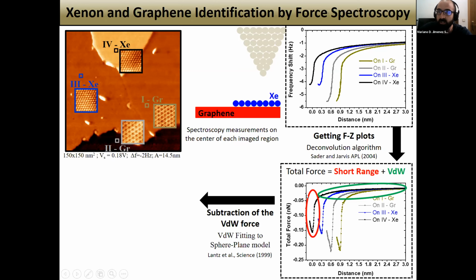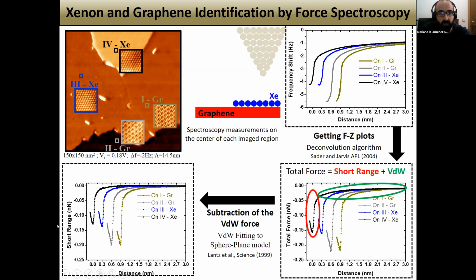In order to isolate it, we have subtracted the van der Waals force, giving rise to these short range distance curves. And what do we observe here? Well, the main thing we observe is that there is a difference in the maximum attractive force that we measure on xenon and the maximum attractive force that we measure on graphene, the lowest one being the interaction measured on xenon.